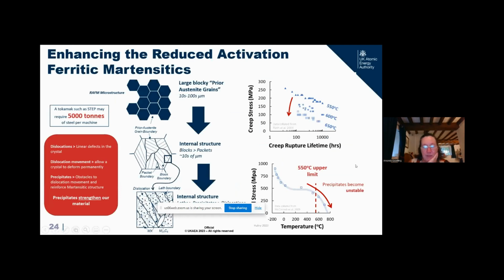So I'm going to dive into that just briefly and say to you that if we take the internal structure of a RAFM and we know that we have prior austenitic boundaries, we'd like to introduce these precipitates on the boundaries, but also inside the grains, so that we have the precipitates act as defect sinks when we get dislocations running through the material from the neutron displacement. But we also want them to be mopping up the gases that are generated through the transmutation reactions. So they act as both defect sinks and they act as gas moppers.